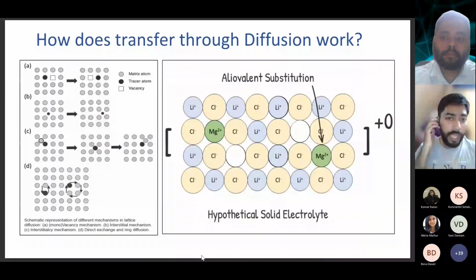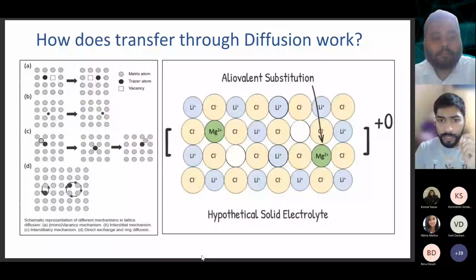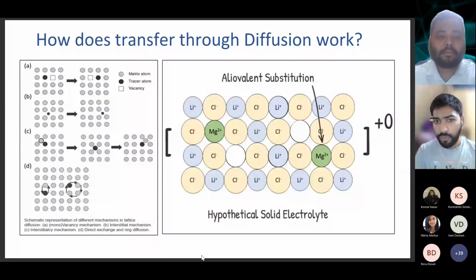So let's assume that we have a structure of lithium and chloride. What we did was, we took out some lithium from the spots, and instead of that, we replaced those with magnesium. We know the charge on lithium is a single positive charge, and magnesium has two positive charges. So to add one magnesium, I'll have to remove two lithium, and so this has eventually created one vacant spot.